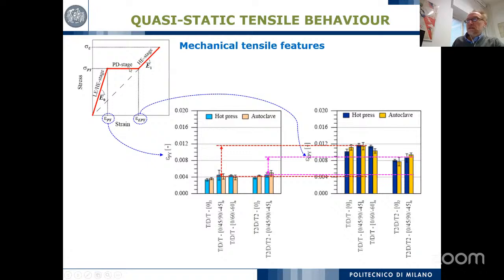In terms of pseudoductility, or the range of strain where this pseudoductility appears, you can see this difference here. As mentioned, this is mainly due to the difference in stacking sequence and the difference in the sublaminate. So managing or designing the proper stacking sequence helps us to increase or decrease the strain range for this pseudoductility. And this is very interesting because we can in some way design our laminate to have a better pseudoductility or a smaller range for this pseudoductility. That is important from the application point of view.